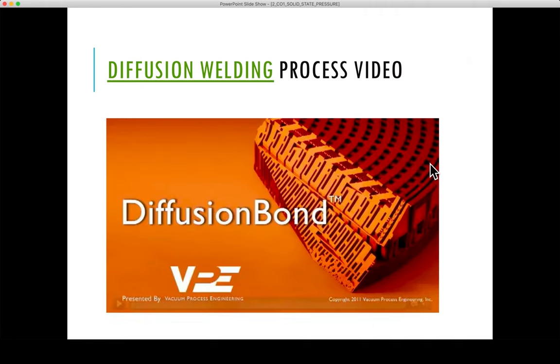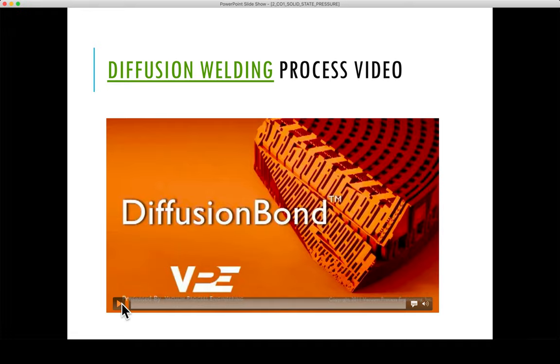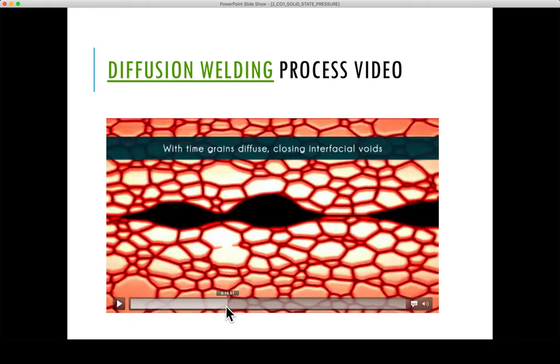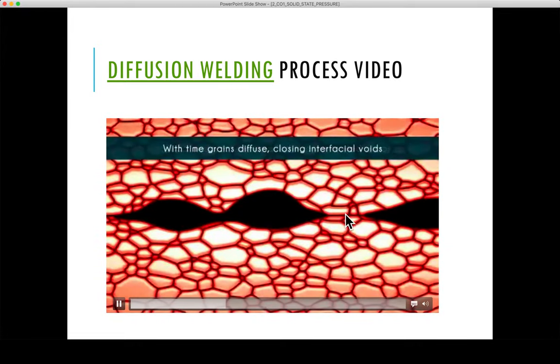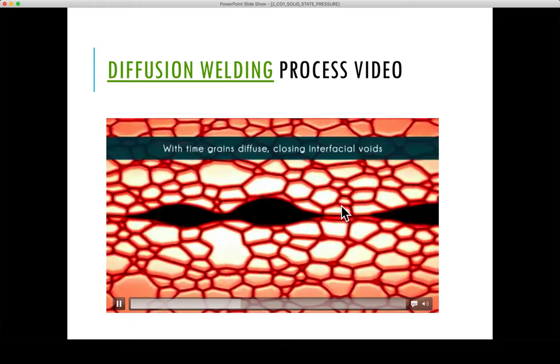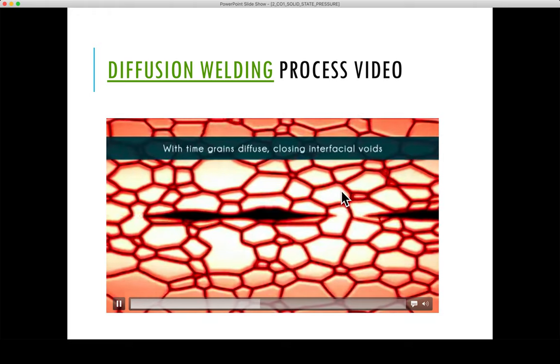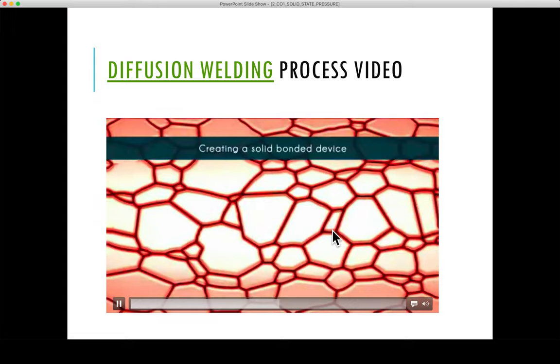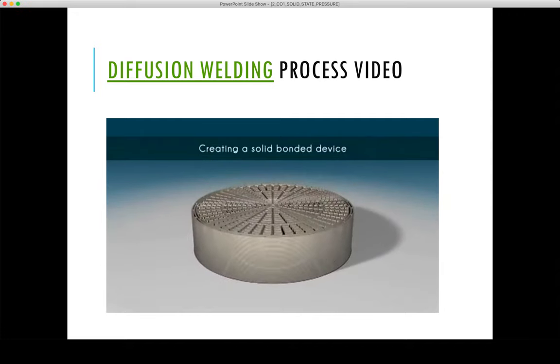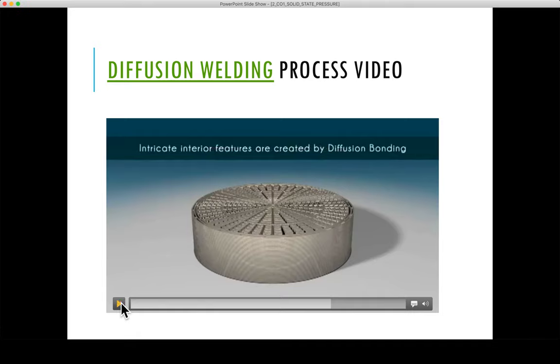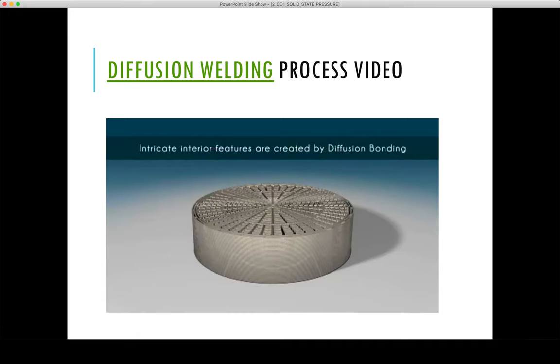This is an example of the diffusion welding process. These are asperity contacts. Once heat and pressure are applied, the yield strength is overcome, the material deforms, diffusion of atoms occurs, new grains are formed, and a pure weld is created. The strength of this weld is basically similar to that of the base material — it looks as though no welding ever happened, like a solid piece of block rather than two plates joined together.